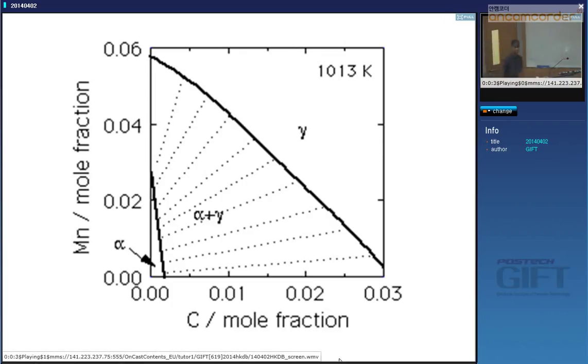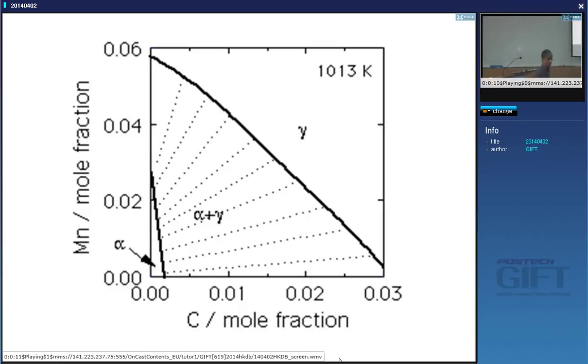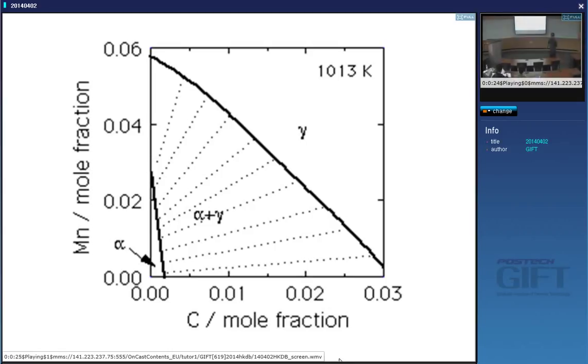You're now very familiar with this phase diagram, which is an isothermal section of the iron-manganese-carbon phase diagram. The important thing to emphasize is that at a constant temperature we can have many different combinations of ferrite and austenite which are in equilibrium with each other. So obviously if I have an alloy of this composition, under equilibrium, this would be the composition of the ferrite and this would be the composition of the austenite.